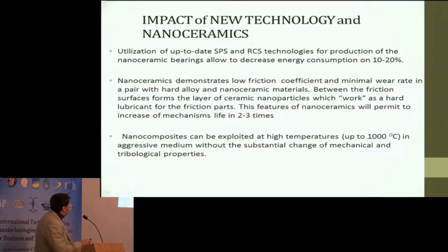Why nanomaterials? We investigated the surface. This one is the counterbody, hard alloy. After friction, a layer of nanoparticles forms between the surfaces. These nanoparticles work as a hard lubricant, and we can use these materials in friction pairs without special addition of lubricant, because nanoparticles are the best lubricant for dry sliding of these materials. We tested our materials for stability in acids and alkali at high temperatures and found that they are quite stable in aggressive medium at high temperatures.